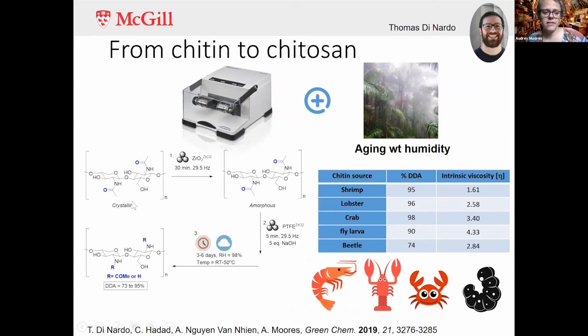So I'm starting here with chitin, which is crystalline, and I'm going to treat it by mechanochemistry. These bowls here are to indicate we're going to do mechanochemistry. And it's going to make my chitin more amorphous, so it's easier to play with. And then I will mix it very shortly with NaOH. At the end of the day, I let it age for some days under high humidity, and it's going to fully convert my chitin into chitosan, which is actually pretty cool because it will use far less energy than the process before. It uses about 1 order of magnitude less water, and again about 1 order of magnitude less chemicals to do this. So it's really much leaner in terms of green chemistry.